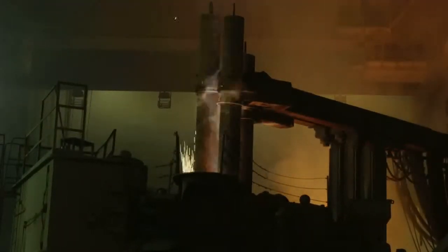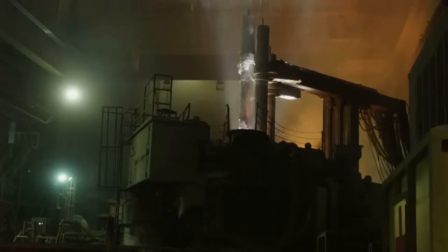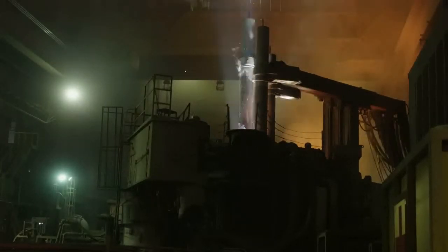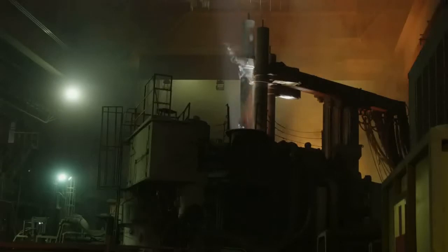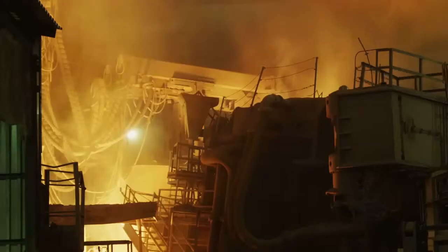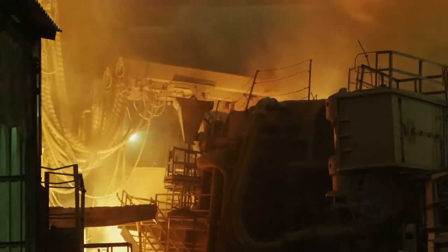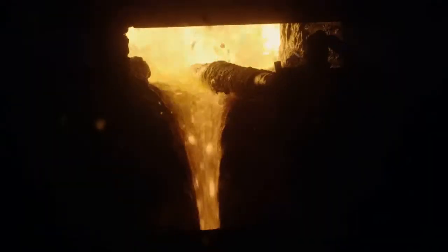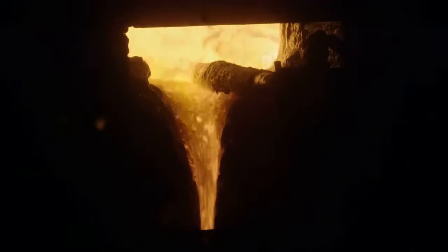And it's loud, very, very loud. The rods circulate or arc up to 115 million watts of electricity to melt the scrap at a temperature reaching 3,000 degrees Fahrenheit. The power is on for about 35 minutes to complete the melting of each heat. Once a heat is completely melted, the furnace is tipped to pour off the slag, a collection of impurities that rises to the top of the heat.